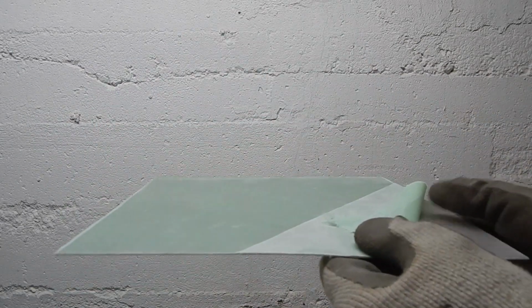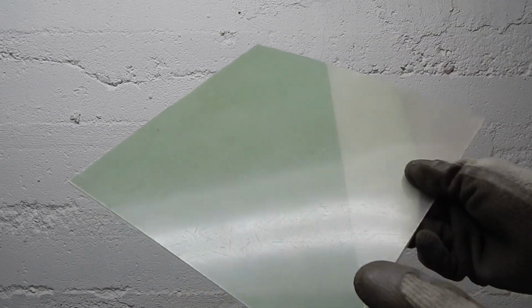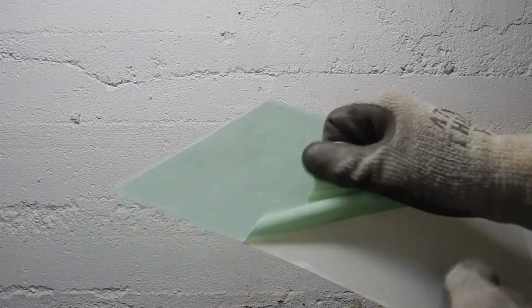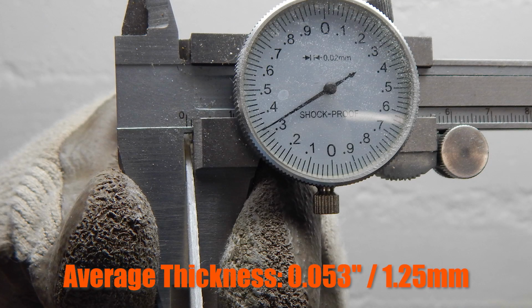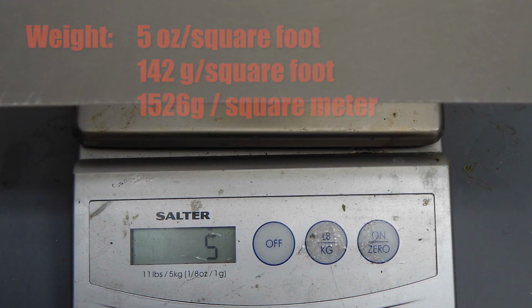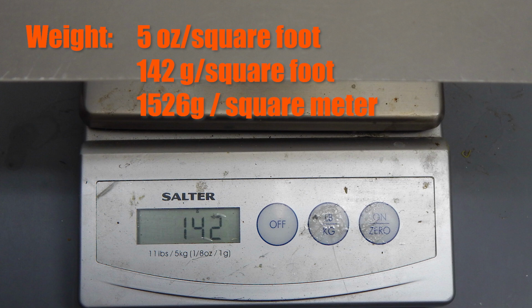Pretty nice, not much air in the surface. You can definitely see fibers printed through. I'm going to pull off the rest of that peel ply, which peels off really nicely because it's coated. The thickness is about 0.053 inches or 1.25 millimeters. 5 ounces per square foot, which is about 142 grams a square foot or 1,526 grams per square meter.